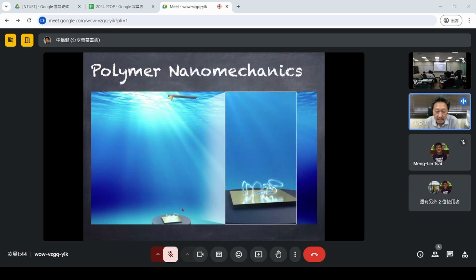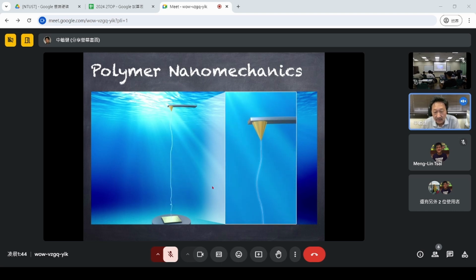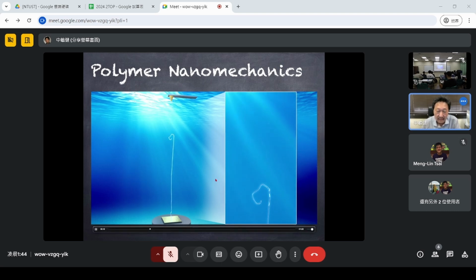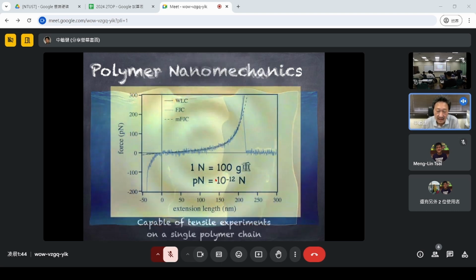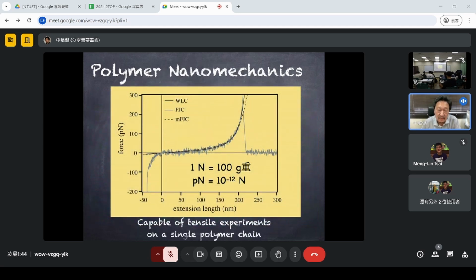I placed a polymer chain in a liquid medium, and one end is fixed on the substrate, and the other end is floating in this way. Then we bring the AFM probe to it, pick up one end, stretch it, and measure the force. This is a cartoon movie, but we can do this using a realistic AFM instrument, and this is one of the results. The horizontal axis is the extension length of the single polymer chain.